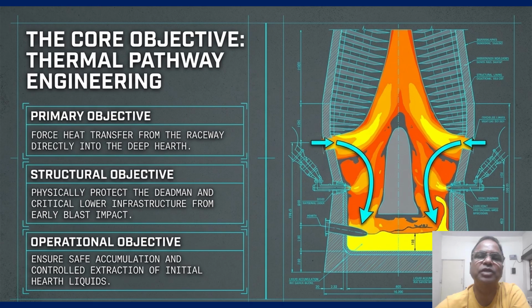Without this, the deadman remains a cold, inert mass that could freeze your first cast. Structurally, we are protecting the lower infrastructure from the initial blast impact, while operationally, we are setting the stage for controlled liquid extraction. The so-what factor is simple. If you fail to engineer this pathway, you will have a hearth full of chilled iron that requires weeks of lancing to recover, costing millions in lost productivity and fuel. So establishing this thermal flow requires a robust internal structure to protect our hardware from the burden's weight.